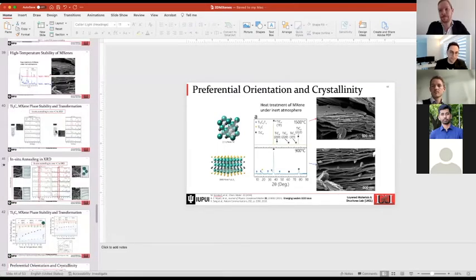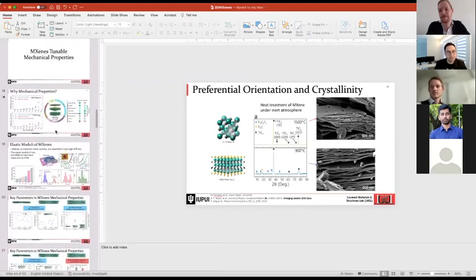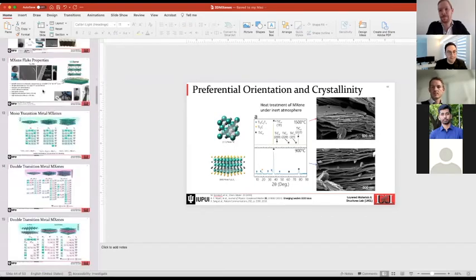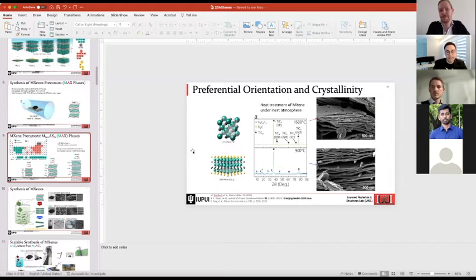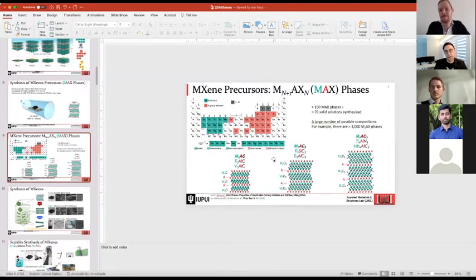To make the layered structure, we need to come up with a different precursor than titanium carbide. That different precursor is these layered ternary carbides, which are called MAX phases. So we are not simply adding aluminum and leaching it out. We are adding aluminum to create a structure that is impossible to make just by using the transition metal and carbon. So by adding aluminum, we synthesize a new phase. It is not just a regular carbide. It's a ternary carbide. It's a family of carbides.